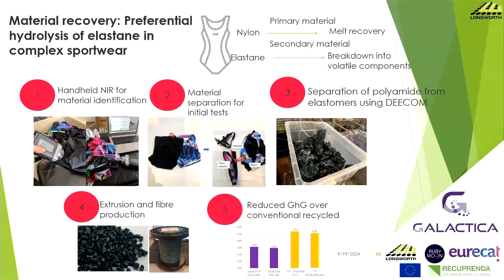And just to show the breadth of this, you might think, okay, well, that's great and all, but when you hydrolyse something, it's going to break down and become useless. In the previous talk here, we talked about how melt flow index is a problem. Well, actually, this example shows we're on the steps to change our levers of temperature and pressure to improve this. This is some work we did with Ruby Moon and some various European labs on the Galactica project, where we took nylon, we took elastane, and because elastane is more hydrolytically sensitive, we're able to change our temperature and pressure variables to retain the majority of the qualities of the nylon while degrading and separating the elastane.